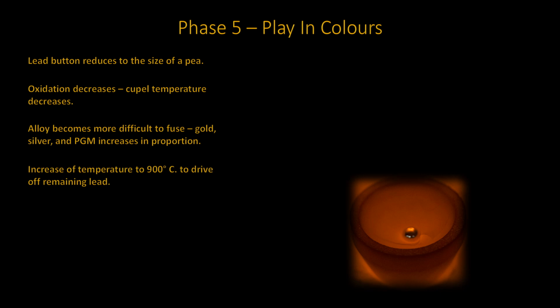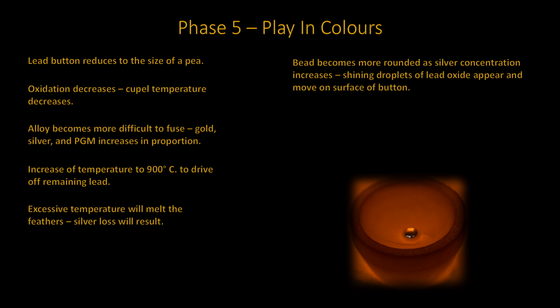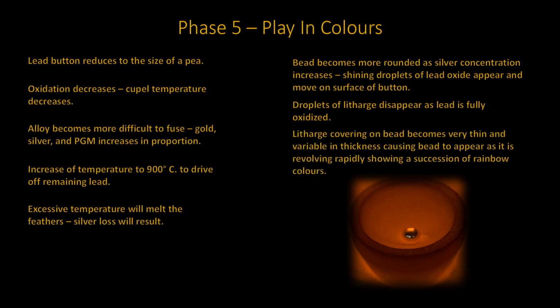The temperature of the furnace at this point must be increased to 900 degrees centigrade. This is done to drive off the remaining lead. If the temperature is raised too high, those remaining feathers will melt and a loss of silver will result. As the bead reduces in size, the silver becomes more concentrated and the bead more rounded in shape. Shining droplets of lead oxide will start to appear on the surface of that pea-sized bead. As the lead is depleted to lead oxide, so will the droplets disappear.